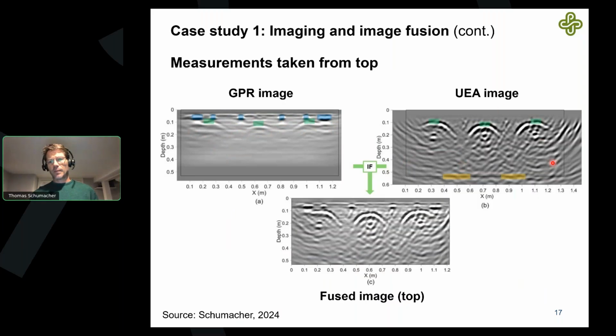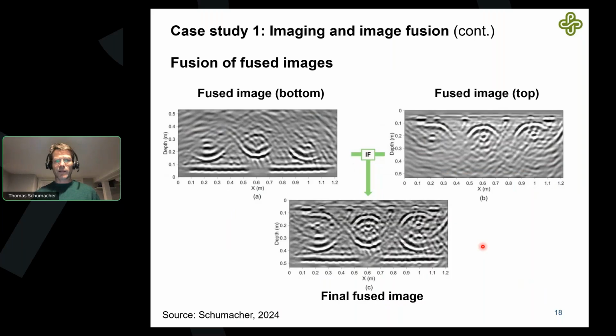The ultrasonic array image, the same thing again. We can see the voids, and we can also see this very nice back wall here, which tells us that the velocity assumptions are correct. We fuse them together, we get this. And then we said, okay, why not fuse the bottom and the top together? So we have this image here from the bottom, we have this image from the top, we fuse them together, and now we basically have a cross section that we can work with. It's still a little bit noisy, but we have all the information in here. We see the voids very clearly, we see the reinforcing on top, we see the pre-stressing strands at the bottom, and we know that they are correct because the reflectors of each match, and we also could see the back wall. So this is now a confirmed image that we can use. We can go in and actually read out dimensions. I will revisit this.